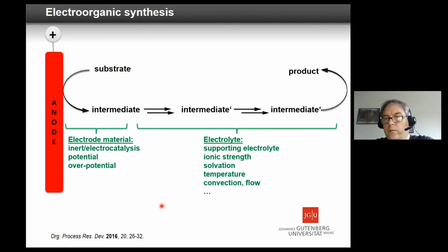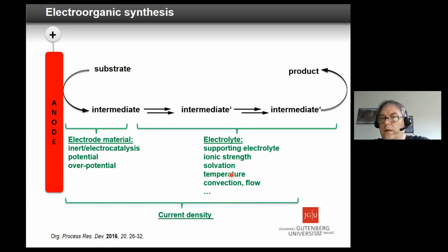And then you have some parameters which are very important, that you have an inert electrode or electrocatalysis involved. Of course, the potential plays a role, but also the overpotential. Overpotential means there are some reasons why some molecules cannot go there or are hindered from being converted. In this area, which goes into bulk, the supporting electrolyte is very important, but also ionic strength, solvation, temperature, flow, and so on. But there's one number which combines both of them. This is the current density. The current density tells you how many radicals are formed close to the electrode, and the concentration of radicals determines which pathway is populated. If you know this, then this number combines both sceneries, and you can easily work with that, because this also indirectly controls the potential. And then the setup becomes much easier and is scalable if you can work with this number.